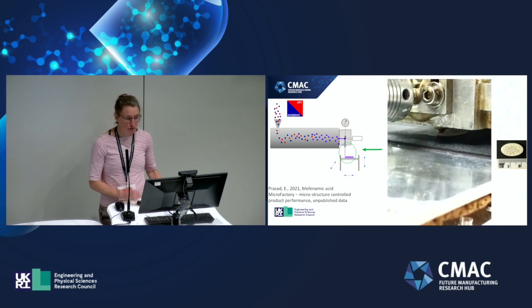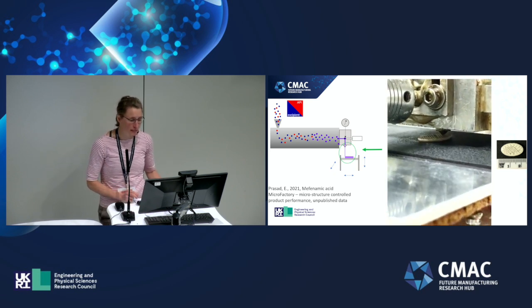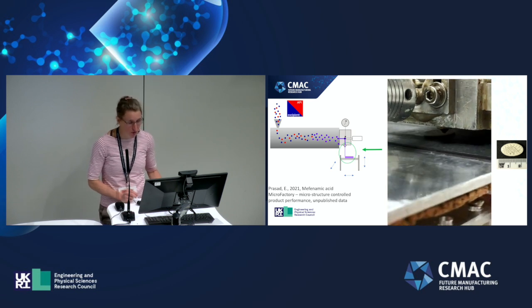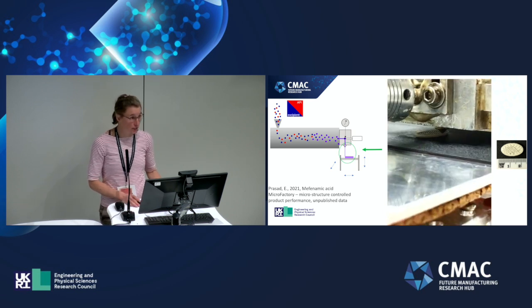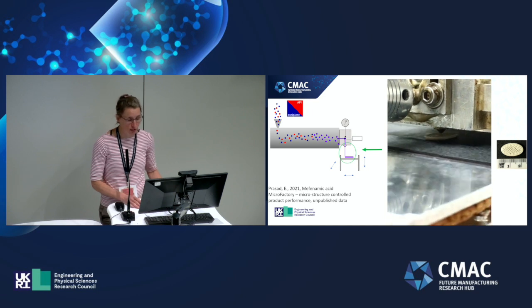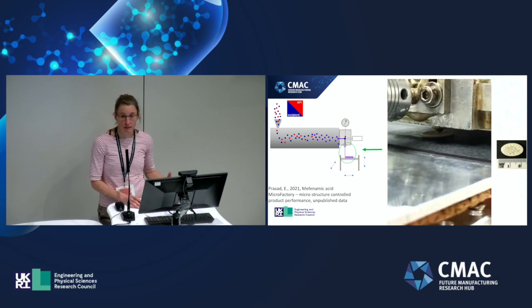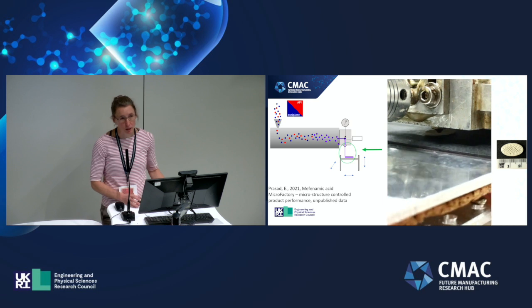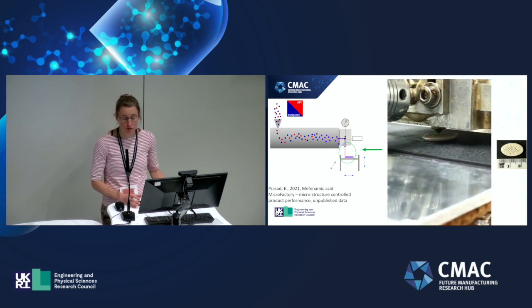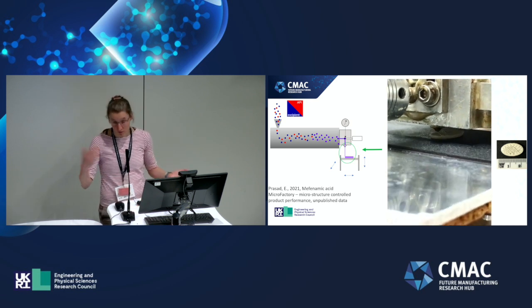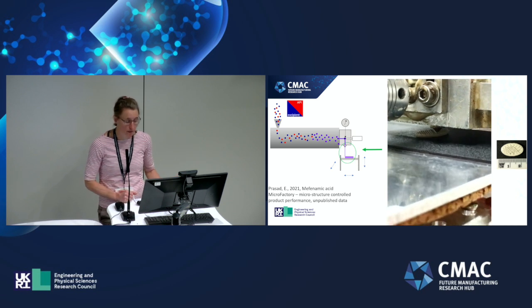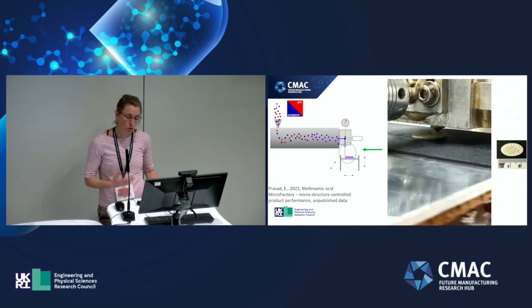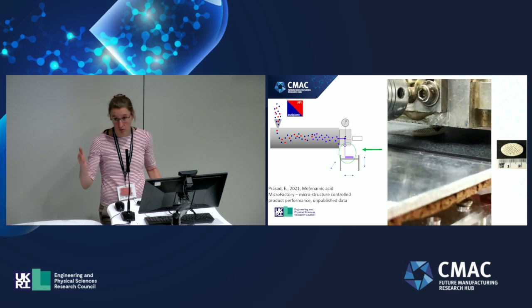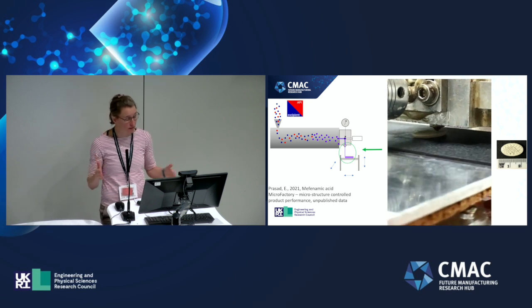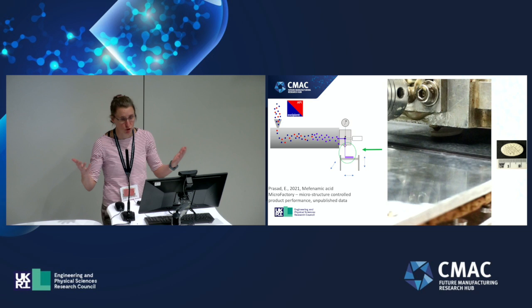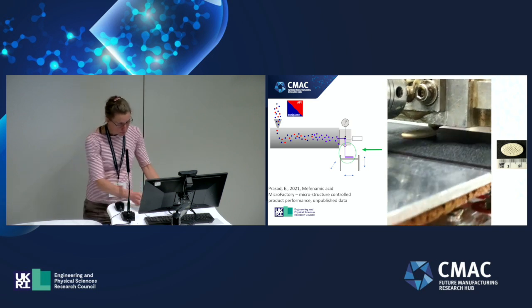In terms of the predictive approaches, or how we can design the process with less material, we use rheology screening tools to identify the initial process conditions. We require about 1 to 2 grams of formulation to do that. So depending on the drug loading, that's obviously less API that's required. And that not only gives us a good initial starting point, but it also allows us to identify where the limits are in terms of the process temperature, for example.